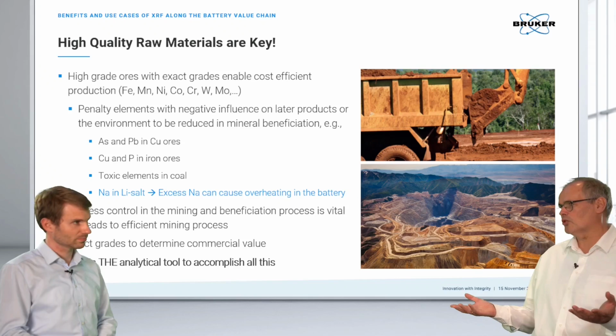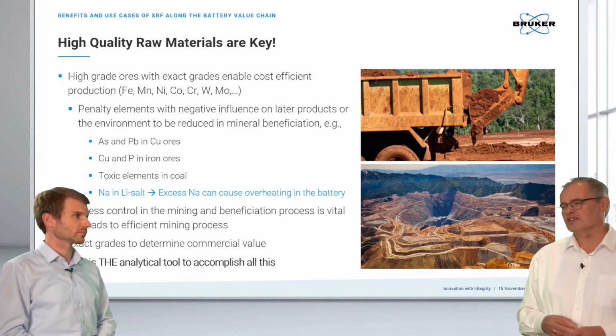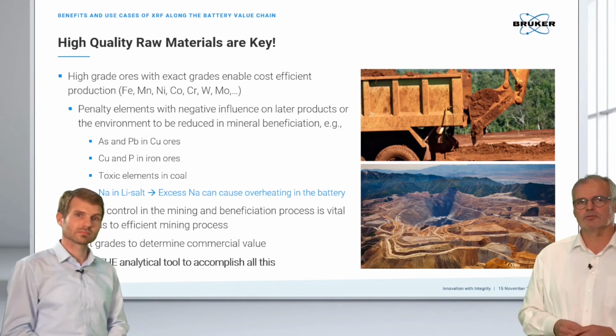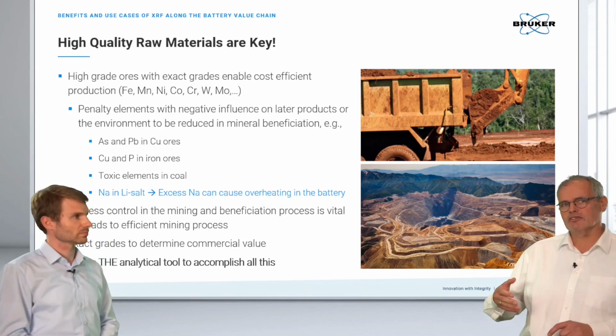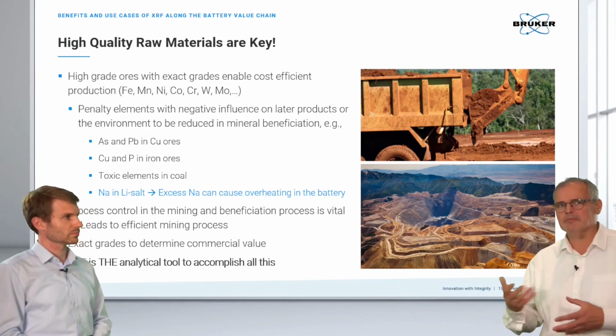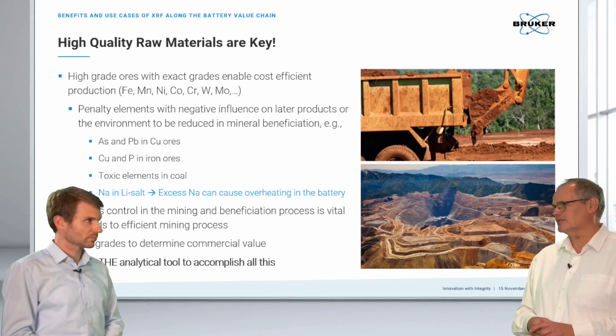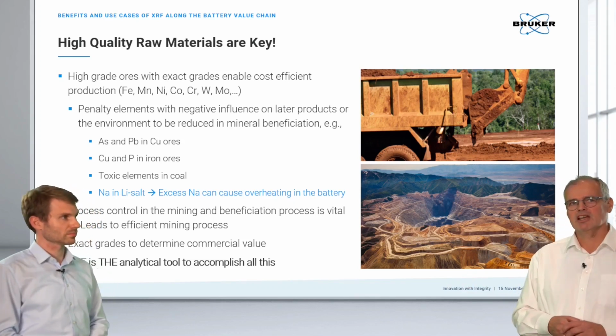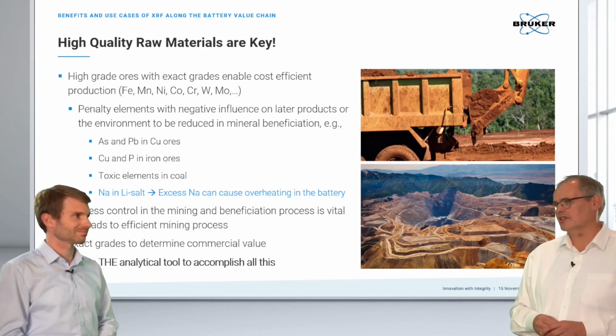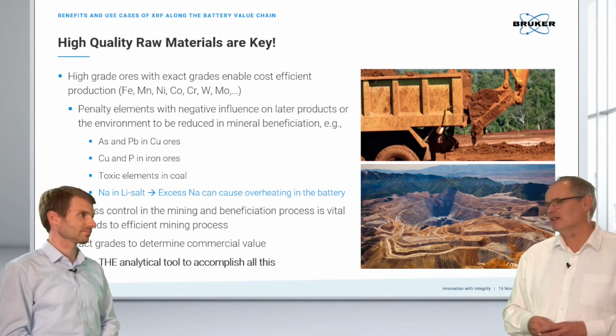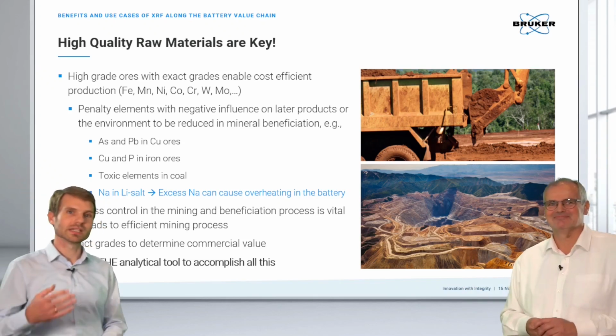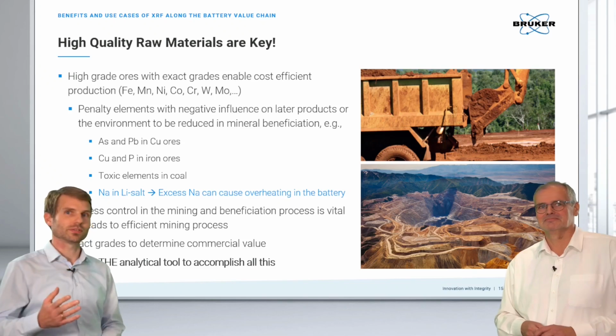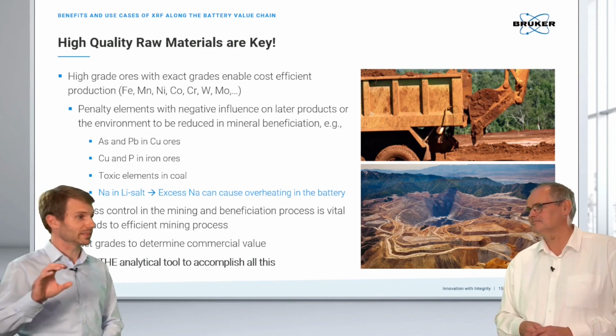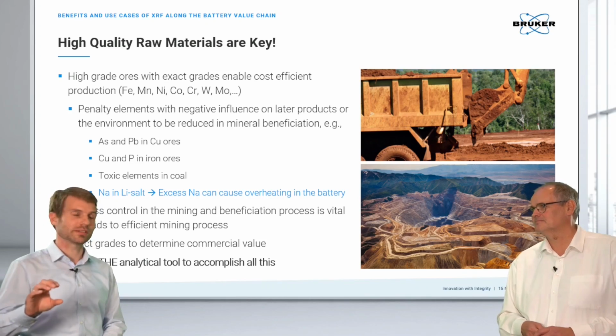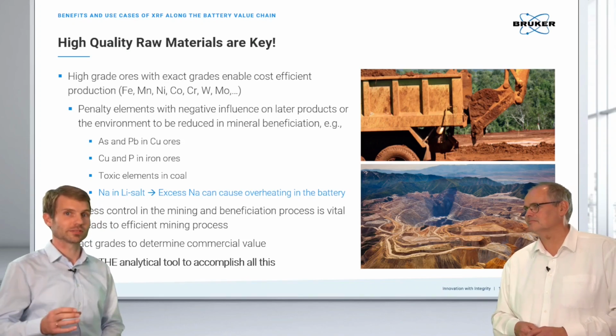Or toxic elements in coal, which will have a negative influence, or the sodium and lithium salts. The sodium can be analyzed by XRF directly, and therefore we can predict what will happen when we use this salt in a battery, avoiding overheating. So XRF is the analytical tool in the mining process, and so better keep it, right? Yeah, exactly. So that's the take-home message for the battery session today: XRF is the established method for these materials. And this means it's probably the ideal method to also check these materials when you receive them.